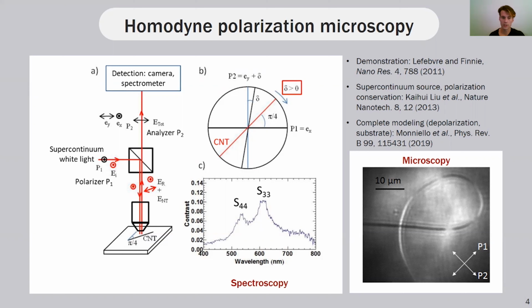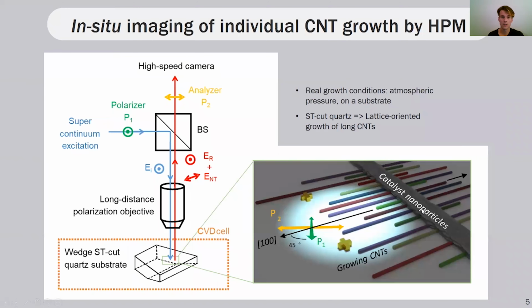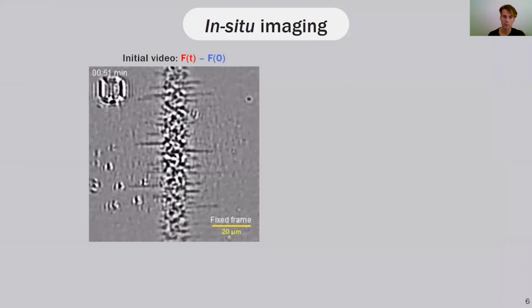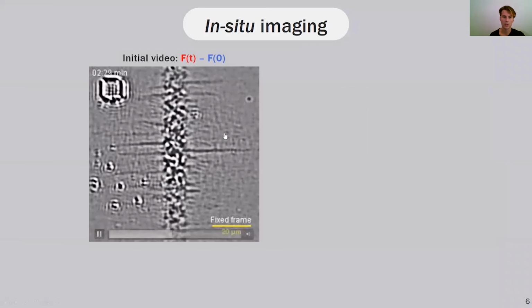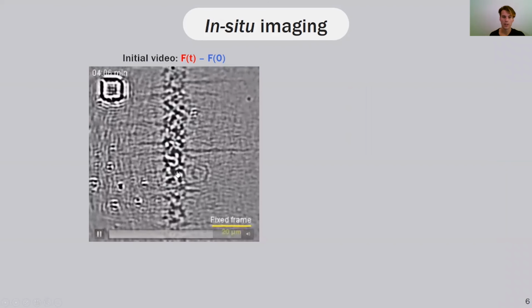And it allows at the same time to measure nanotube optical spectra or make images of them, as shown here and there. We applied this technique to make a video of nanotubes growing in real conditions, such as atmospheric pressure and on a substrate. As a substrate, we used monocrystalline ST-cut quartz because it has the advantage of favoring nanotube growth along particular directions. And we put the sample so the nanotubes grow at an angle of 45 degrees between two cross polarizers. The video we obtained with this technique, you can see here, and you can see that nanotubes grow horizontally aligned from this catalyst line.